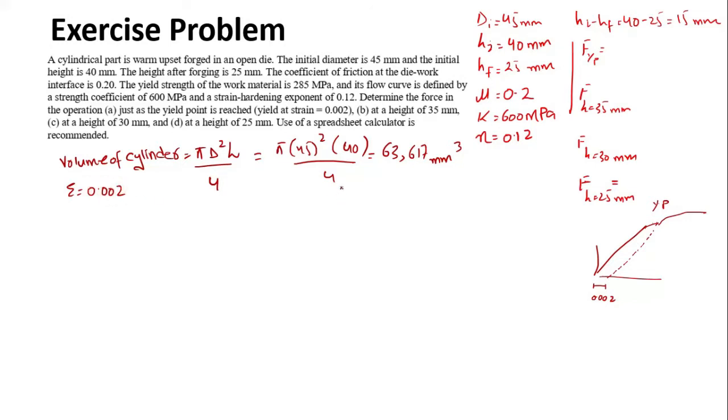Now at this strain, the flow stress would be equal to the strength coefficient into the strain raised to the strain hardening exponent. That would be 600 megapascals into 0.002 to the power 0.12. So the value of the flow stress would be 284.6 megapascals.